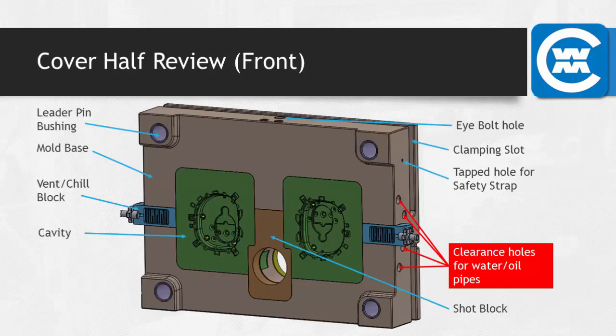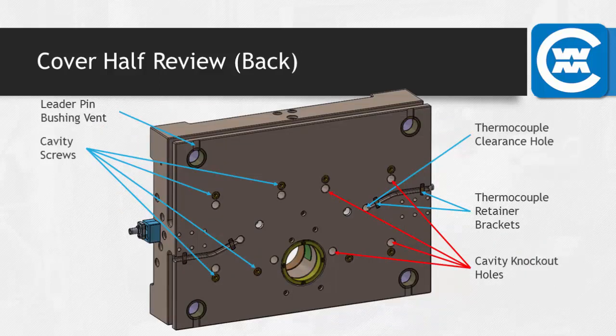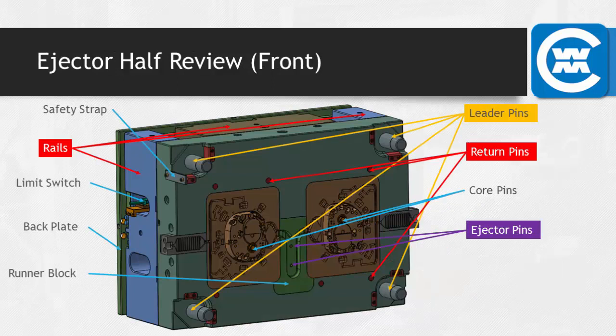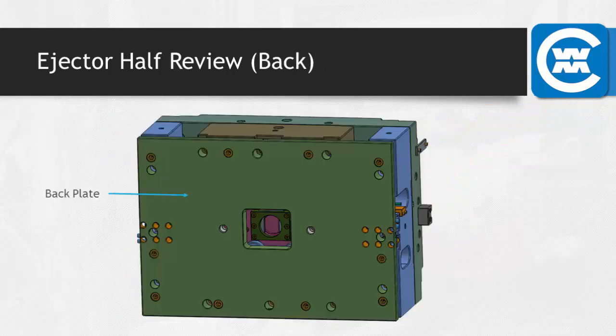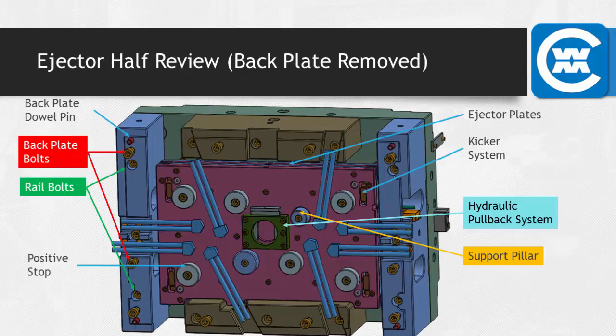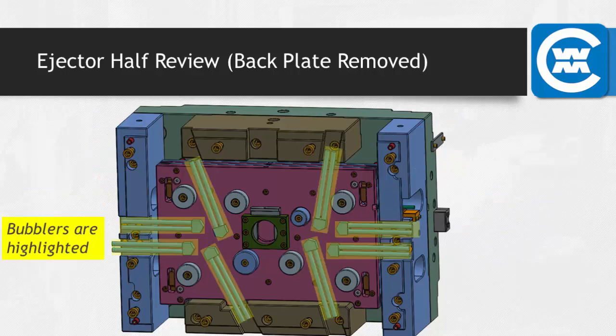We won't spend too much time on these overview slides. This is just to give you an idea of how the whole die is assembled and works together. So this is the front of the cover or stationary half, and the back of the cover stationary half. The ejector half is a bit more complicated on the front than the cover half. Not so bad on the back of the ejector half, but let's get rid of the back plate and see what's underneath that. And it's a bit more complicated. So this is showing the back of the ejection system that moves forward with the ejector pins to push the part off the mold. The rest of the components you see on here support the die against the back plate for even pressure distribution on the platen. Or they could have cooling components, so we'll get more into these bubblers a little bit later.